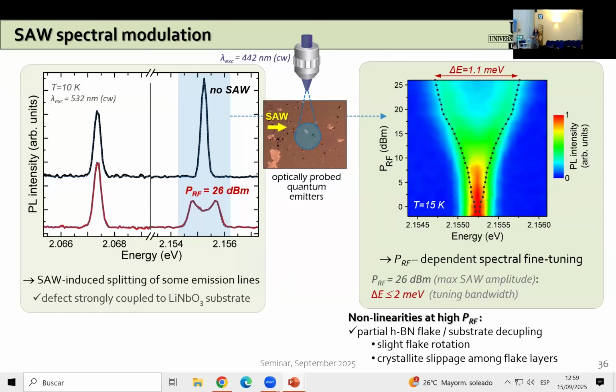You see here that, as opposed to nanowire quantum dots, at higher RF powers there are some non-linearities appearing, and they probably come from a slight decoupling of the flake from the substrate. This can be induced by a slight rotation of the flake, or by slippage among different layers within the flake. But the fact that not all emission lines are affected by the acoustic wave shows that not all defects have equally strong mechanical coupling to the substrate.